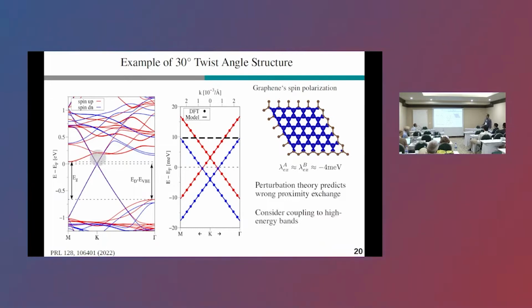If you consider perturbation theory, you would expect that the Dirac states would couple to these energetically closest spin-up substrate bands. However, if you would do that, then the spin-up Dirac states would be pushed to lower energies because energy levels that are coupled repel. However, this is not what you observe in the DFT calculation, and it's actually rather the coupling to high energy bands. In particular, you will find such a pronounced anti-crossing of spin-down Dirac states to substrate bands. And this is, in fact, pushing the spin-down Dirac states to lower energies.